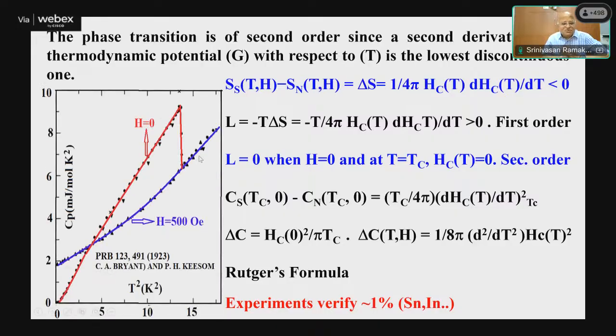Okay, so this is how the heat capacity was explained by the Ginzburg-Landau theory. You can see that this is the data for the tin experiment, and the heat capacity increases like this, and then shows the superconducting transition at close to 3.7 Kelvin. Then it becomes a normal state here. And when you apply a field of 500 Gauss, the superconductivity is quenched, and you can see that the normal state heat capacity goes like this in the blue line. You can clearly see this jump at the critical field, suggesting it is a second order phase transition, and that jump is proportional to the critical field squared divided by pi Tc.